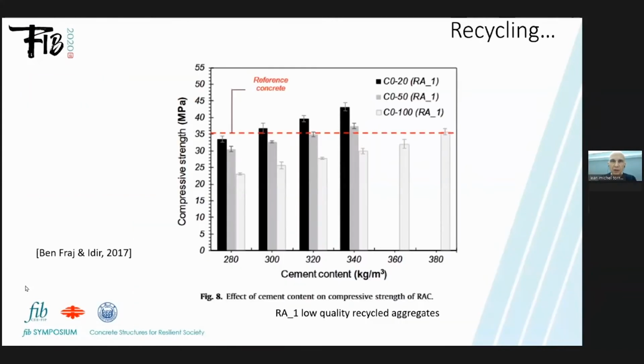But we know also that if we don't have a high quality recycled aggregate, we have to increase the cement content. Here it's a study of Amor Benfrage and Mrs. Idir from Cerema, and they have compensated the use of a larger amount of recycled aggregates, which are low quality recycled aggregates. It means there are a lot of wood, plastics, bituminous materials, not only concrete aggregate. And you see that you have to increase the cement content to obtain a given strength. When you have 100% of aggregate, of course, a lower amount if you have 50%. But even if you have only 20% of recycled aggregates, you have to increase slightly the amount of cement.